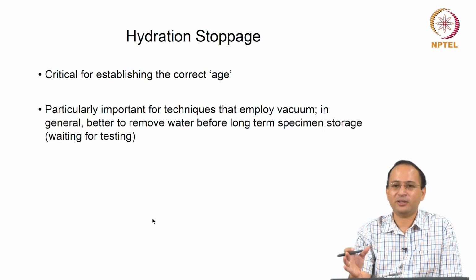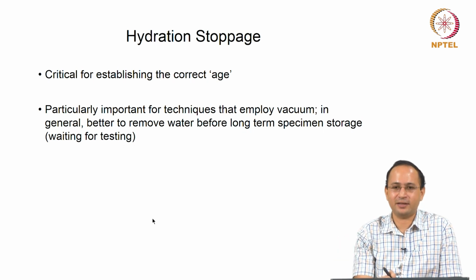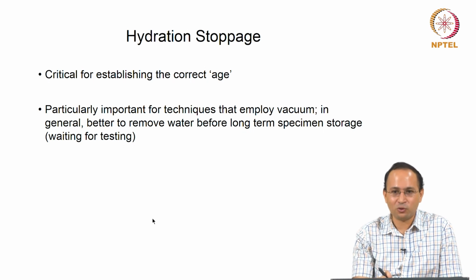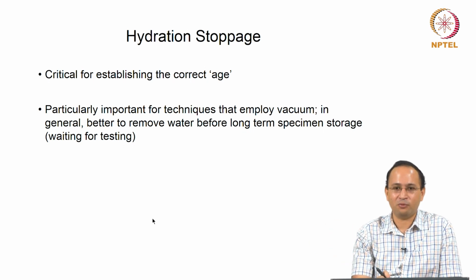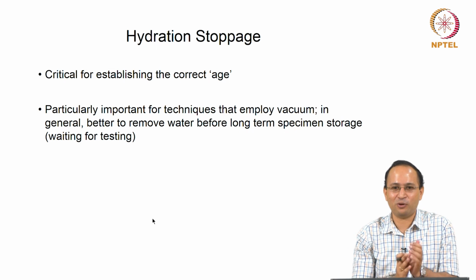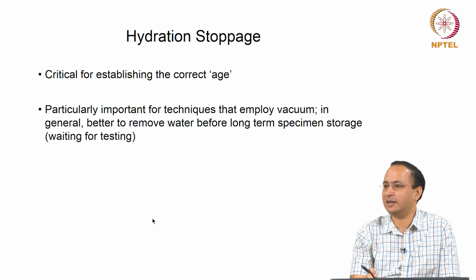But there are a lot of other techniques which you will learn, like in this case X-ray diffraction, scanning electron microscopy, and other characterization techniques. For that you have to make sure that you are stopping the hydration, because a lot of techniques are sensitive to water. First of all, SEM you can't carry out on a hydrated sample without treatment. XRD may not get affected, you can still do XRD, but since you are not following different sample preparation processes for different techniques, usually we want to follow the same sample preparation technique, then get the sample and use the techniques, right.